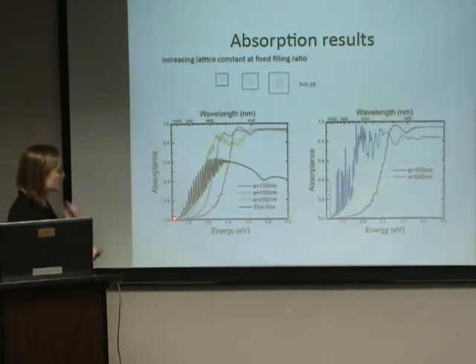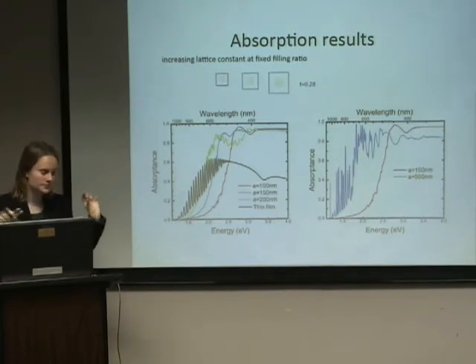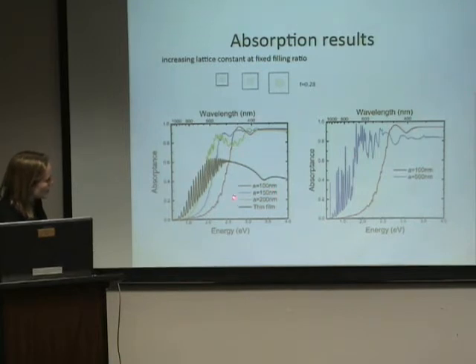So this is the absorptance as a function of energy. And the black line is what happens if you just had a film. Forget the nanostructure. It's given here. And then these are the results for nanowires as you increase the lattice constant. So you see down here for the 100 nanometer lattice constant, you do worse down here, and then you do better than the thin film up here. Turns out that if you take the integral, overall it's worse. As you increase the lattice constant, though, the whole curve shifts over to where for the green case, you're really doing significantly better than the thin film.